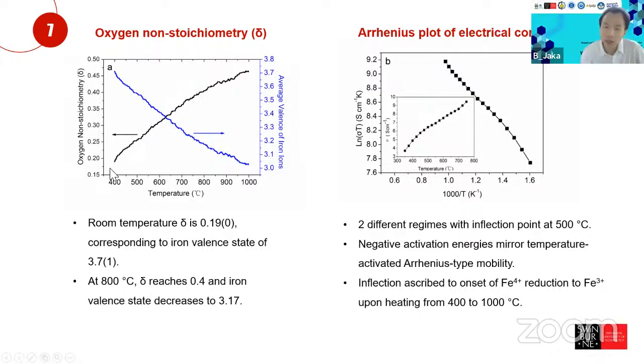Okay, so that is very important because the performance of the oxygen deficient perovskite can normally be correlated with the oxygen non-stoichiometry in the perovskite. And then the next one that we want to check is the electrical conductivity, or the electronic conductivity. So the electrical conductivity in here is the sum of the oxygen ionic conductivity and the electronic conductivity.